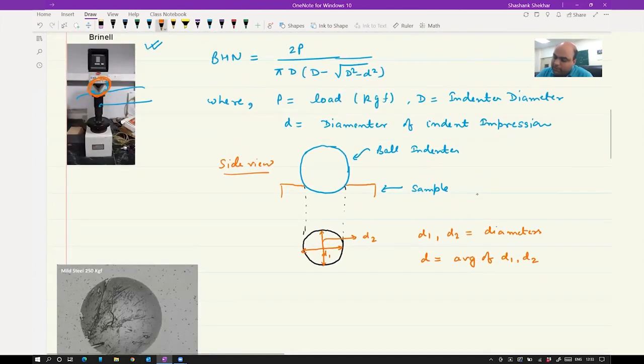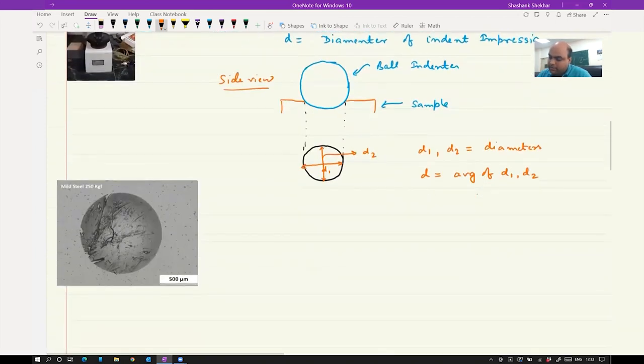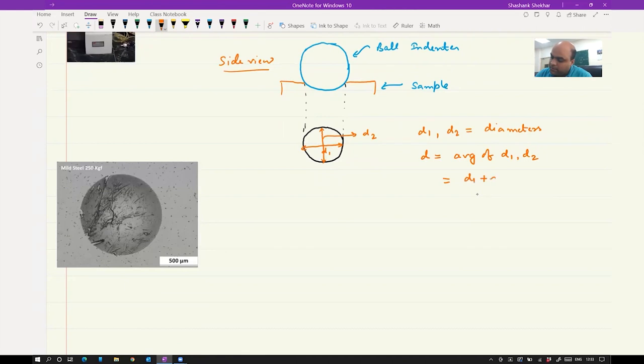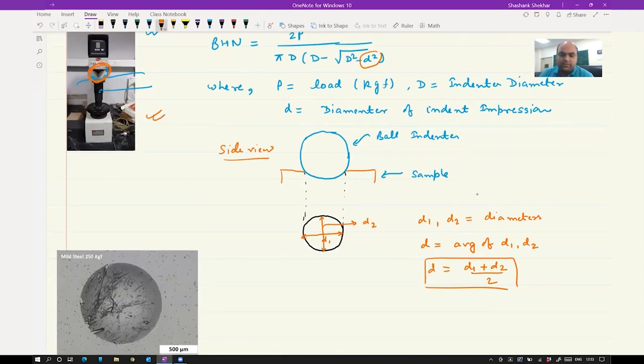So this D, if you remember, is here. Okay, so this will be D1 plus D2 by 2. You know P because you are doing the test, and the ball diameter is also given to you. So what you have to do is use this indenter, take out the sample after indentation is done, and go to a microscope, see the top view, and you are going to see a circle. Then measure the diagonal diameter along two perpendicular directions. Those will be D1, D2. Take the average of those two, and that will be small d.